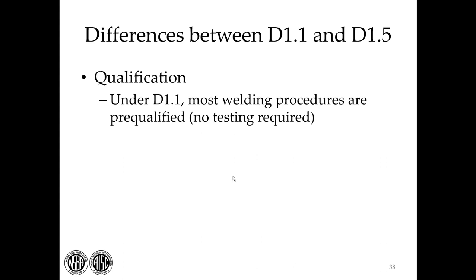But typically, the welding that we're doing in bridge fabrication and that most structural fabricators use, they are within the realm of what's pre-qualified under D1.1. So if you're looking at using D1.1 versus D1.5, you're not going to have qualification testing. However, you will have practice and associated requirements for welding procedures that will give you good, sound welds. That's the intent of how D1.1 is set up. It's intended so that if you specify it and the fabricator follows it, then you can be assured that you'll have the proper material properties in your weld metal under D1.1 without doing the qualification testing.